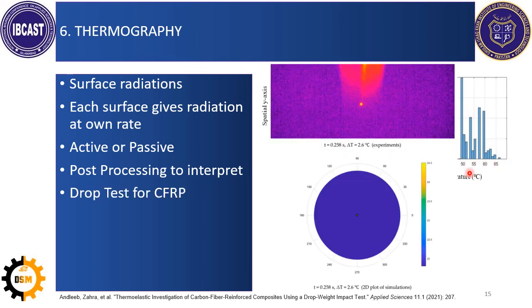Another work was done by my PhD student Ms. Zahra. In this work she used CFRP laminates. These are pre-preg laminates. We worked in collaboration with UiT Norway. In that work, a specimen ball was dropped on the carbon fiber polymer laminates, and this is the spot of that drop, imaged using a high resolution thermal camera. You can see there was a small amount of energy released when we dropped a ball on the surface.